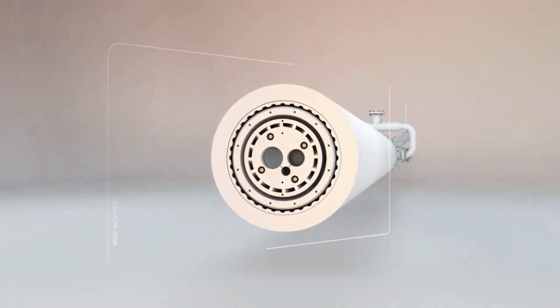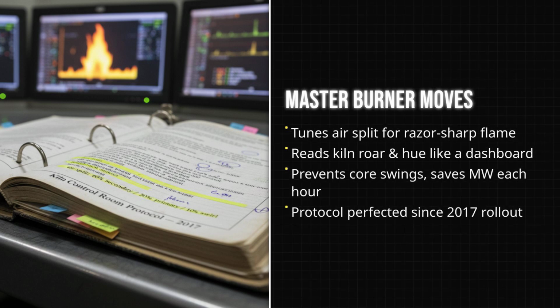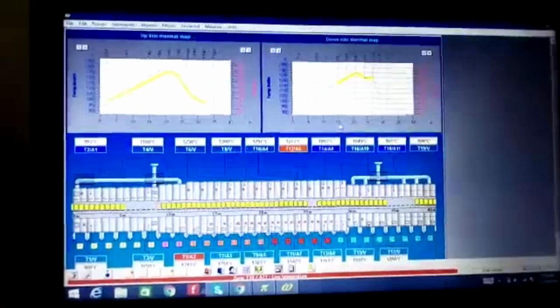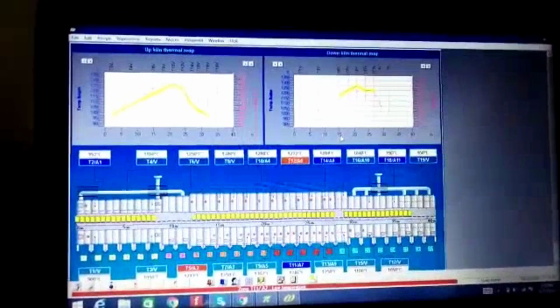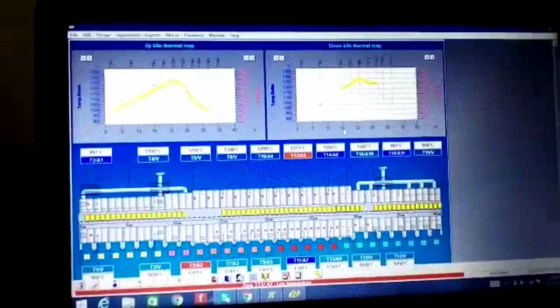Maria adjusts the primary air, a cool, high-velocity jet that cores the flame, while the secondary and swirl air jets wrap around it, shaping the plume's length and turbulence. Her protocol, refined over years, calls for a strict air split: 60% secondary, 30% primary, 10% swirl for standard coal. She tweaks these ratios in real time.